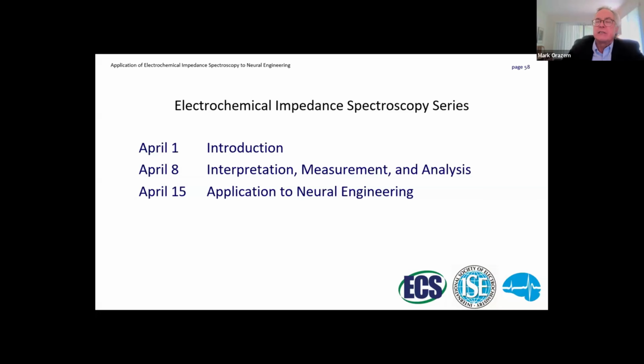So in other words, you can look at the local current density and compare that to the local potential and then calculate impedance based on that local current density. And then you could basically scan that probe along the surface and see how the local impedance changes. I've seen some really cool work done like that. I don't do that in my group, but basically we're saying it's a completely different approach toward impedance spectroscopy. But if you really are interested in the heterogeneity of your surface, that would give you a way to explore that.